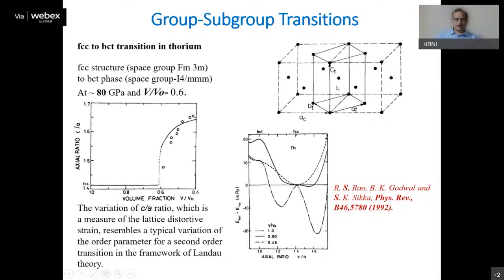But it has been observed, like in this case of thorium, at about 80 GPa, when the volume drops to about 0.6, when V by V naught becomes 0.6, you start getting an increase in this c by a value.